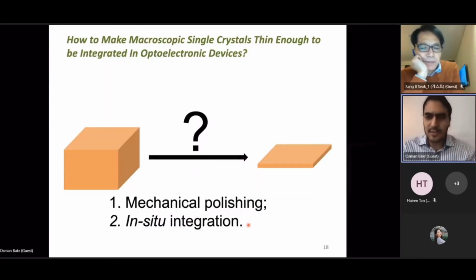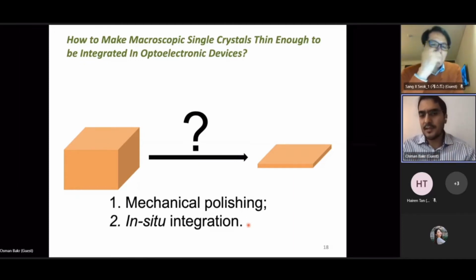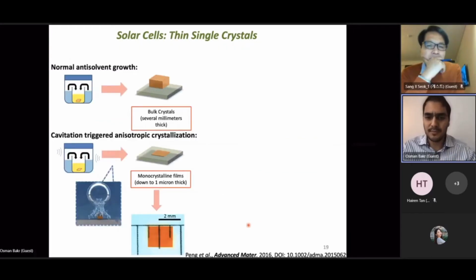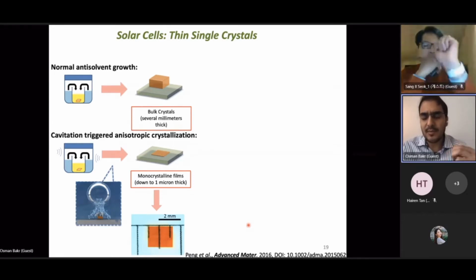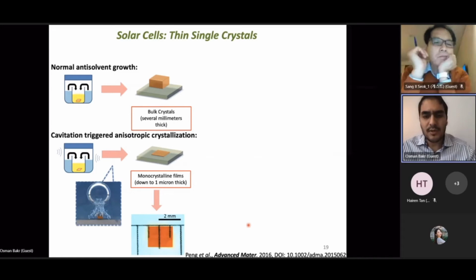So the second question that came up for us was, we have single crystals, they're nice for fundamental studies, but can we use them for devices? And to use them for devices, you have to make them thin enough for device applications, and that requires either a way of slicing them or mechanically polishing them, or ideally you find a way of actually growing them thin enough to begin with. In our first method to grow them, we found that if you introduce a sonication pulse before supersaturation, you actually create a cavitation pulse that spreads the crystal on the substrate.